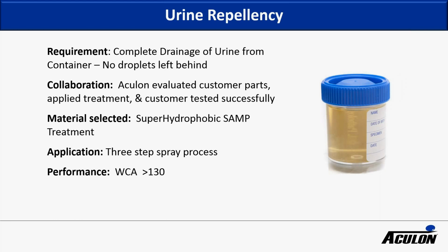Another example where we've commercialized is in urine repellency. A company came to us and said they had a container and wanted essentially no droplets of urine left behind in this container. This application doesn't see mechanical abrasion, so we used our superhydrophobic SAMP treatment. It's a 3-step process with very high water contact angles and good performance. And so this was tested and carried out successfully.